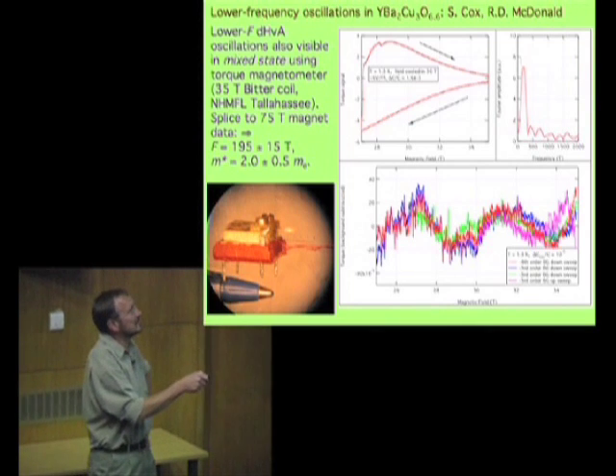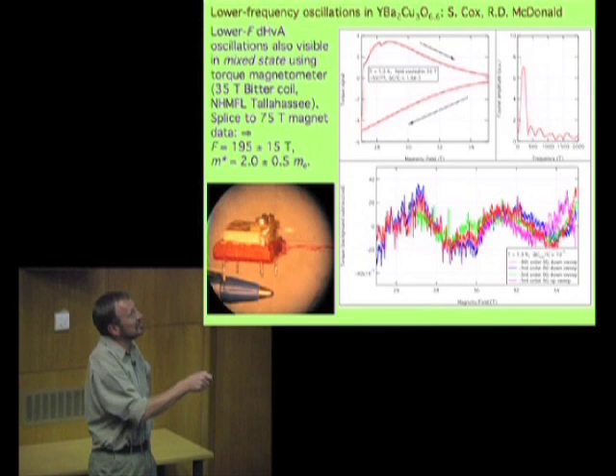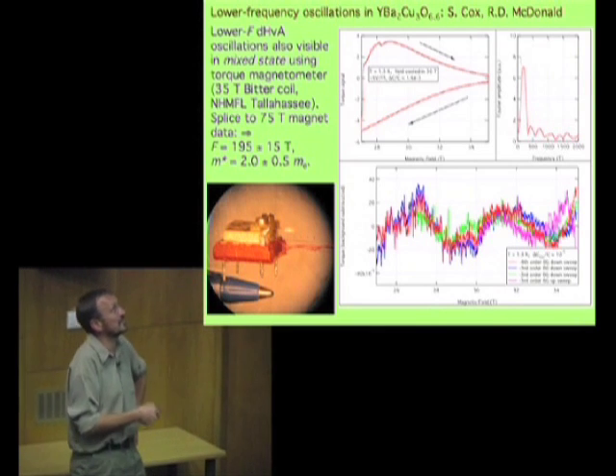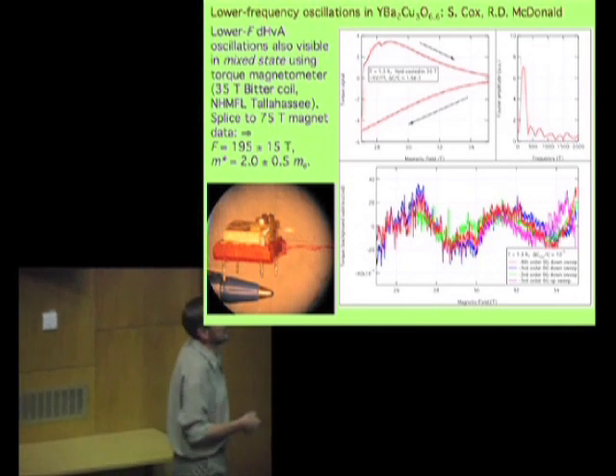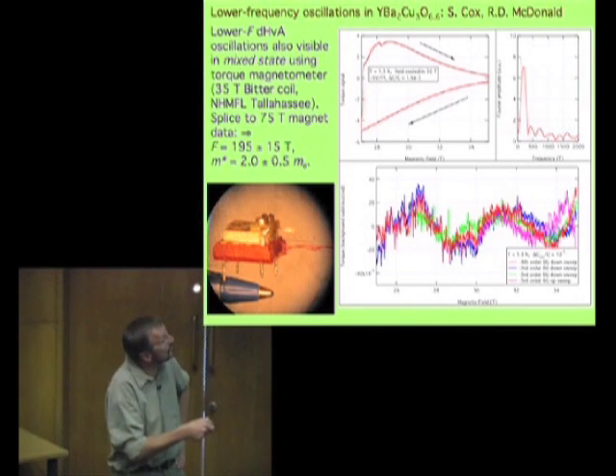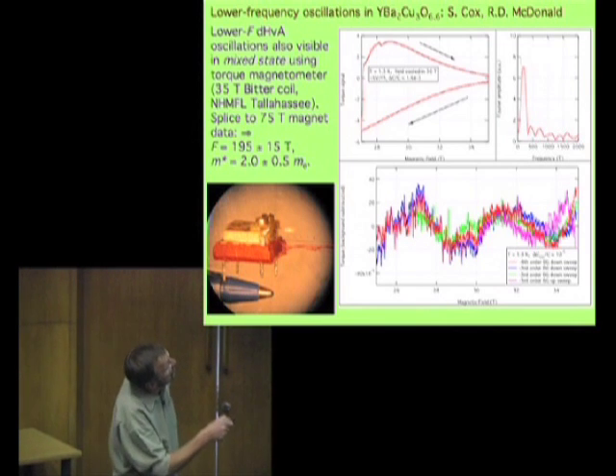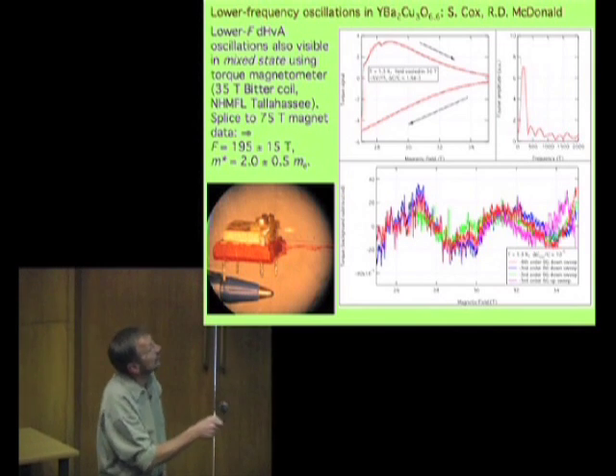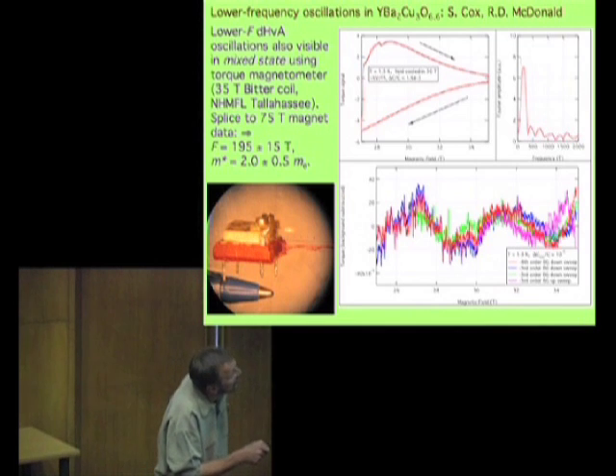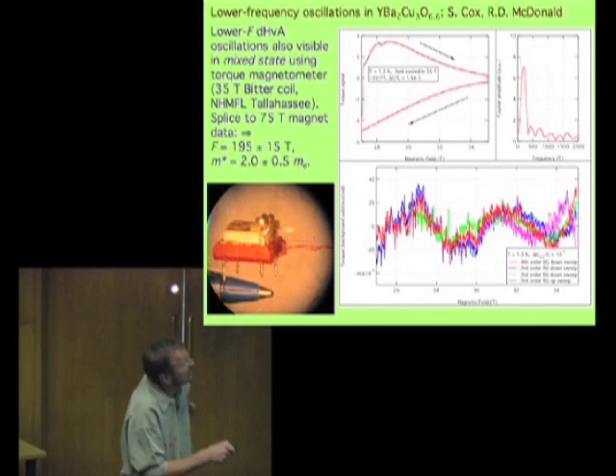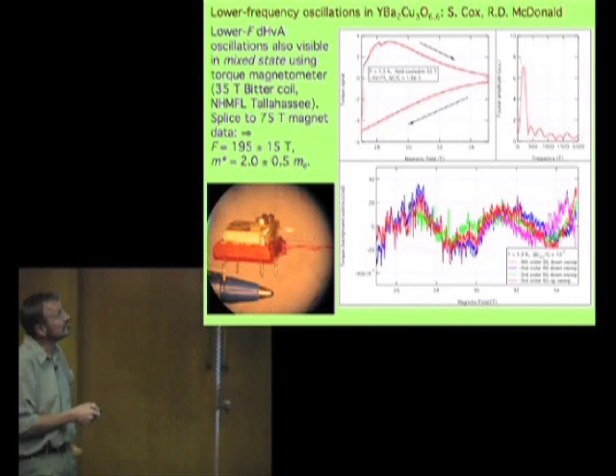When the sample's magnetization changes, the torque on this cantilever changes, and that changes the capacitance between this ground plate here and the springboard. And it's a very, very sensitive method of getting out magnetization. And lo and behold, in the torque, once we've subtracted the background due to the fact that we're in the mixed state of the superconductor, you again get these oscillations of a low frequency.